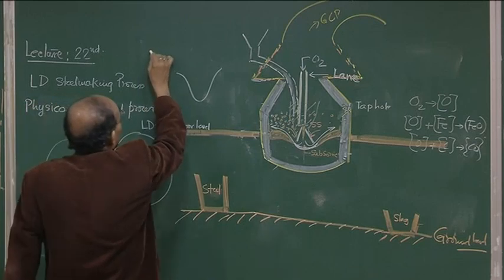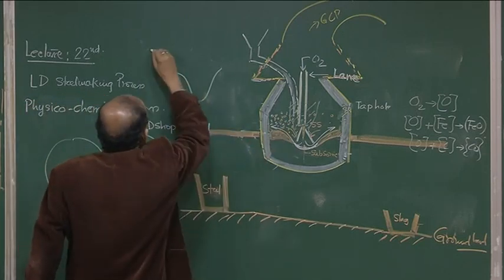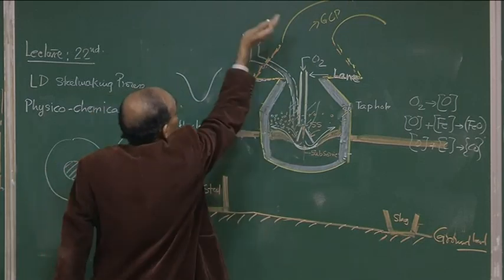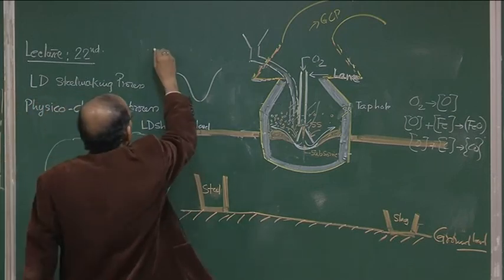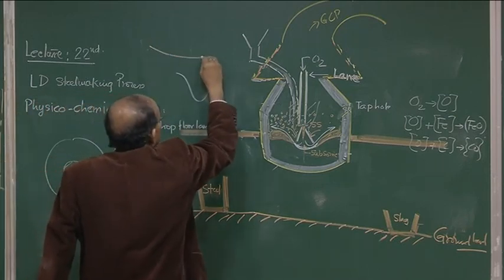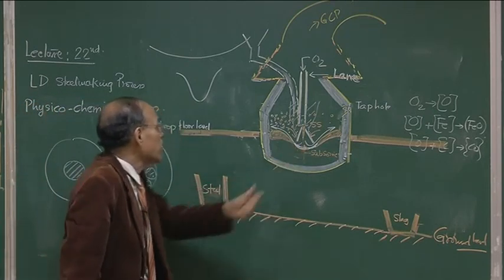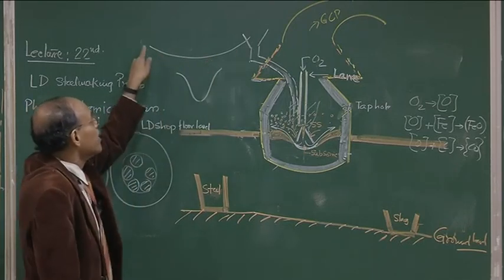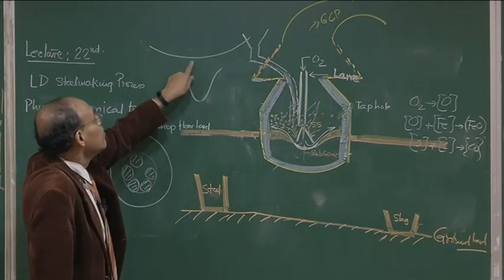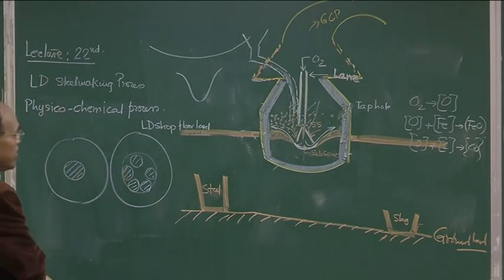On the other hand, in a soft blow, you have retracted the lance vertically upwards, so there is a significant amount of distance, and possibly the depression, the cavity, will have a configuration like this. So the surface area exposed is very large, but on the other hand, the gas has lost quite a bit of momentum, so you will not be able to generate